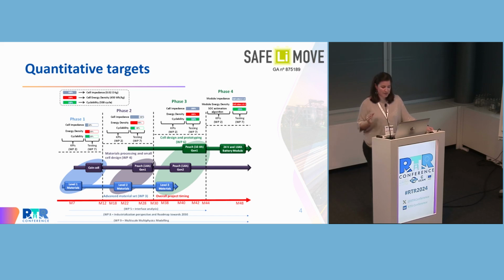So in the first phase, we developed our level 1 material. We consider this as the proof of concept where all the different components were put together, and we needed to learn and understand the compatibility. And these were used to produce the Gen 0 monolayers or coin cells of the project. From the learning we gained here, we developed the level 2 materials. That in this case was a scale up to produce the first generation 1 ampere-hour cells of SAFELiMOVE. Again, guided by this knowledge gained through the cycling, aging, and post-mortem analysis, we developed the last generation of the materials of the project, level 3 materials.